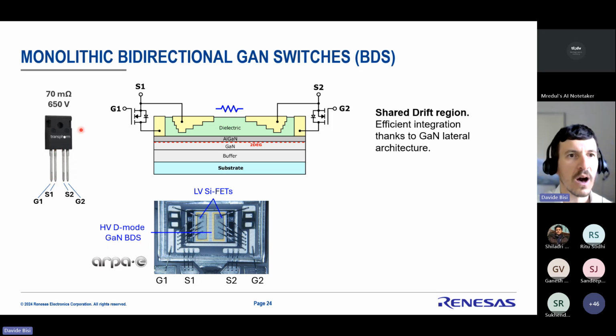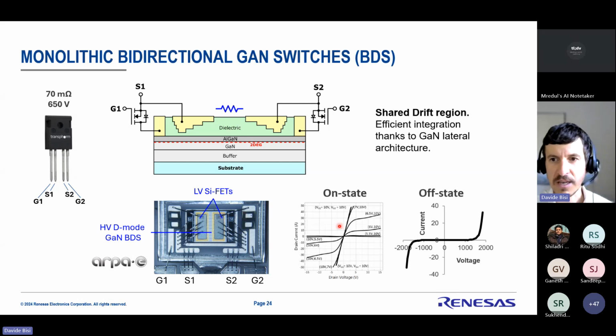You can see here a prototype of a 70 milliohm, 650 volt bidirectional switch with two sources and two gates. The way it's assembled is as before. We have the GaN chip with the two silicon FETs on top of it, so we don't have any additional area or additional wire bonds for the cascode configuration. And you can see here data: we have bidirectional current flow, so we can flow current in both directions. And most importantly, we have bidirectional voltage blocking capability, so we can block voltage both in the positive and the negative direction. So this is a very important feature, and the reason is coming in the next slide.